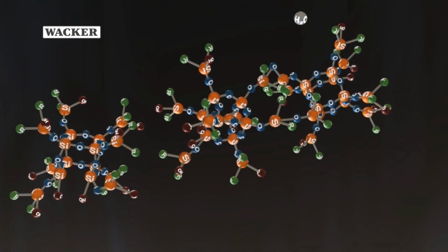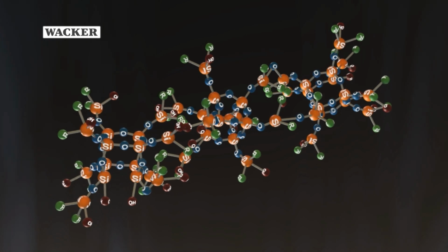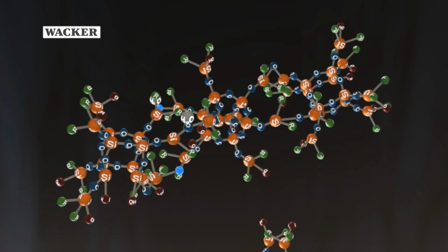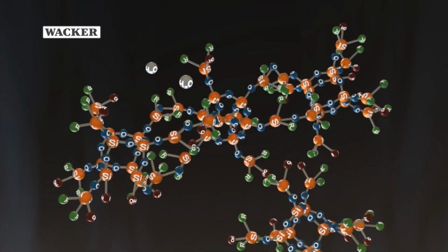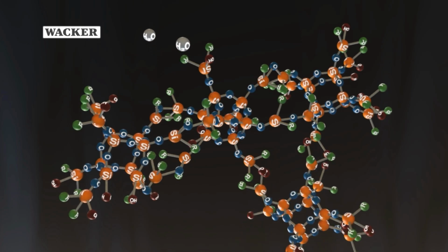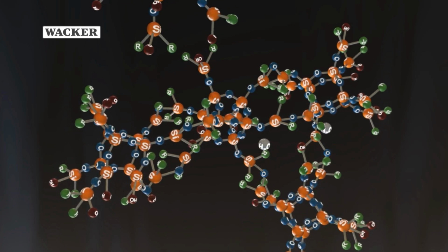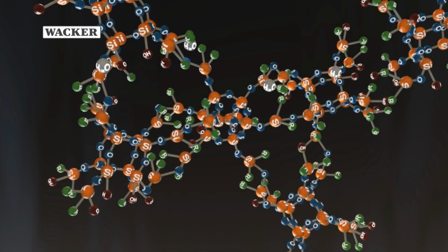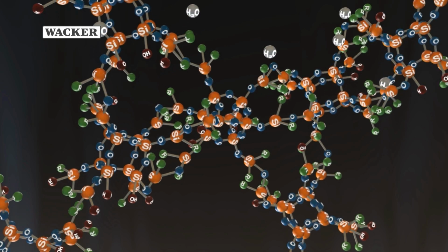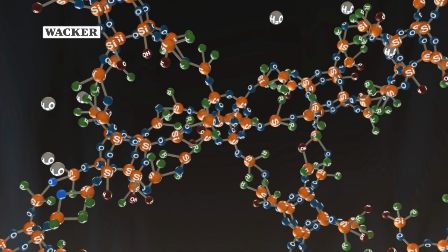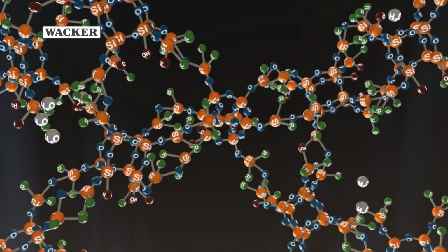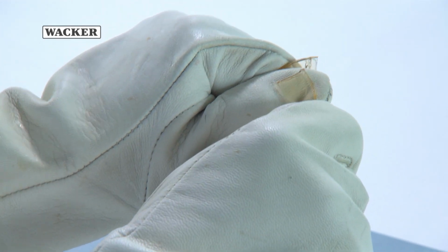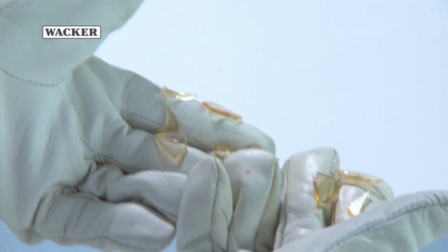Cross-linking at the surface doesn't continue until the silicone resin undergoes significant heating and, in some cases, has been mixed with suitable catalysts. This, in turn, releases byproducts from the resin. Depending on the type of resin, these can be water or an alcohol, such as methanol or ethanol. Once complete, curing produces a very dense network, which is why the cured resin is relatively hard and brittle.